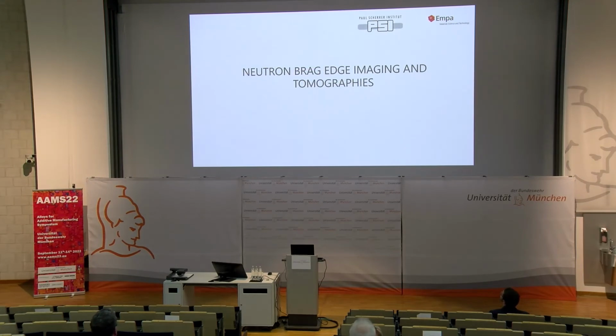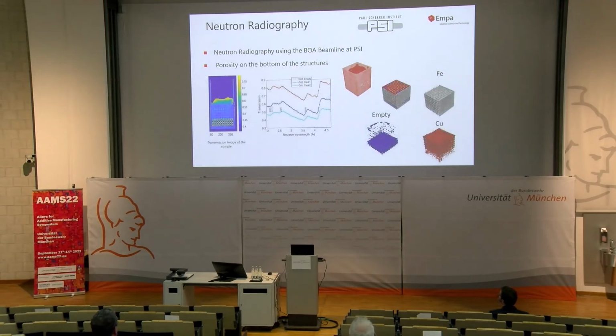Finally, in order to have a look at the crack and the porosity formation, we conducted some neutron Bragg edge imaging and tomography measurements at Paul Scherrer Institute. For both of the measurements, we used the cold neutron-based beam lines, BOA and ICON, and we had the option to go either for neutron radiography, neutron imaging, or neutron tomography. The latter is the one that we paid more attention to. We can reconstruct the sample by focusing on distinguishing the steel and the copper. And from the first analysis, we can see the appearance of porosity at the lower interface between steel and copper.